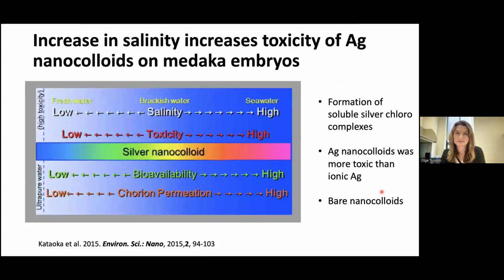To make matters more complicated, salinity can actually increase the toxicity of silver nanoparticles. Why? Because when we have fresh water and there is just a little bit of chloride present in the water, the silver will form pretty stable, basically not dissolvable, compounds. However, if there is an increase in salinity, then there is formation of soluble silver chloride complexes. And actually, there is an increase in toxicity in this case, in this study in Medaka embryos.